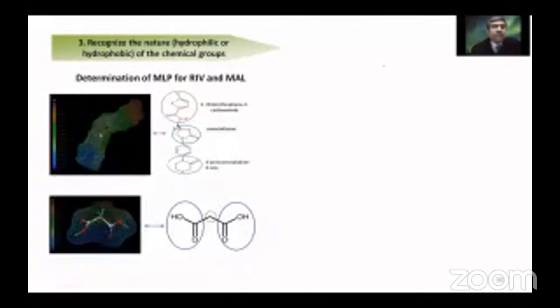So we did it for rivaroxaban. The blue colored zones show the groups which are relatively hydrophilic, and the brown ones are the groups which are hydrophobic in nature. So these are the hydrophobic groups of rivaroxaban, while these are the groups which are relatively hydrophilic in nature. We calculated the molecular lipophilic potential using the in silico method, and this was the malonic acid molecule. As you can see here, most of the molecule is hydrophilic in nature, as it is blue colored throughout the molecular structure.